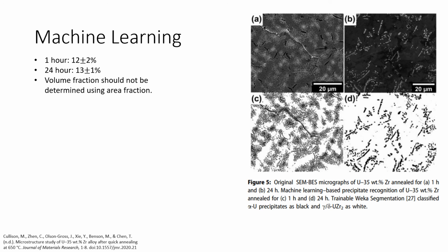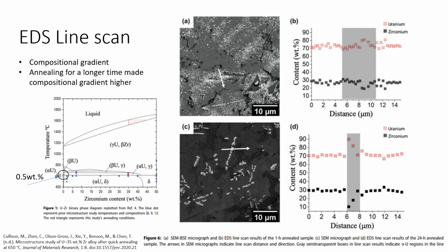Machine learning determined that the area fraction of the precipitates was roughly 10 to 14%. It's important to understand that relating area fraction to volume fraction is not possible. Even assuming perfect spheres can show a large uncertainty. The important information we did find was that uranium travels to the grain boundaries, which may have implications for fuel behavior, such as fission gas retention, material strength, and thermal conductivity. This work may support fuel performance codes, manufacturing, and core design.